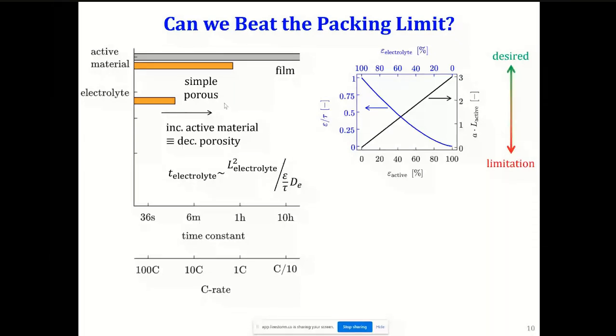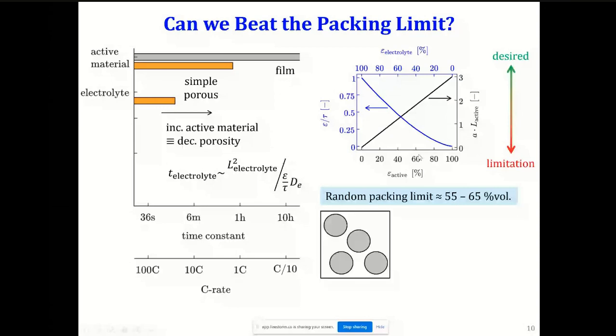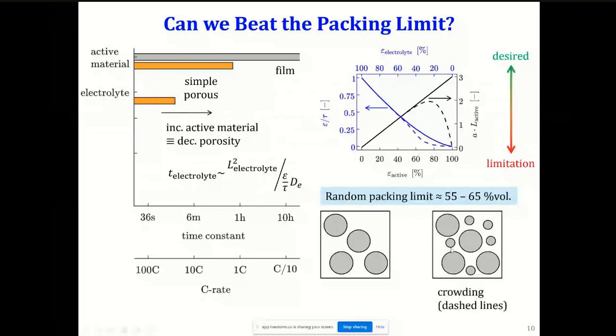Now, this is not the end of our troubles, because what we are missing here is that there's a limit on how many spherical particles we can pack in, right? The typical limit is about 55 to 65% for random packing, which would mean that we are sort of cut off somewhere in the middle of this plot. Now, someone may pose that we can get by that by having a bimodal distribution or having smaller size particles. The issue with that is you would now start seeing these crowding effects, where your electron transport becomes sluggish and the small particles which are caught up between large particles wouldn't intercalate as easily. So all these things would further put limits on these issues, and you would gradually become more and more transport limited.